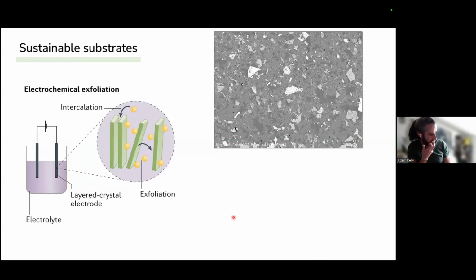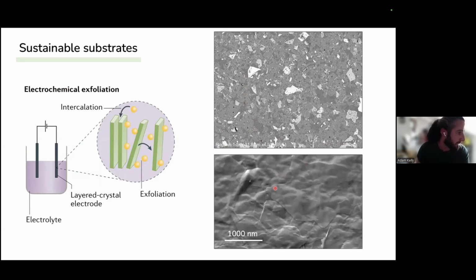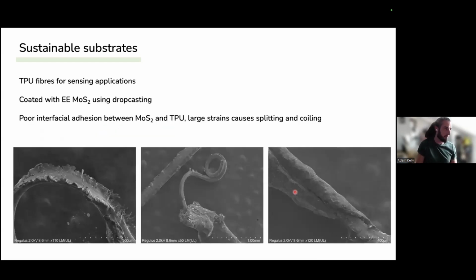A master student came to me recently and said she wanted to produce some sensors by coating molybdenum disulfide onto a fiber. If we want to do a coating with a two-dimensional material, we need large area thin monolayers. And if you want to create nanosheets that have very large basal planes and are monolayer thin, you need to use electrochemical exfoliation. Now, this works by intercalating compounds in between the sheets. And when you put them in a sonic bath, then you break them off gently and you get these large area monolayers. Now, this is good for when you're making networks because they sit very nicely on top of each other. You get all this van der Waals bonding and you create a strong conformed network.